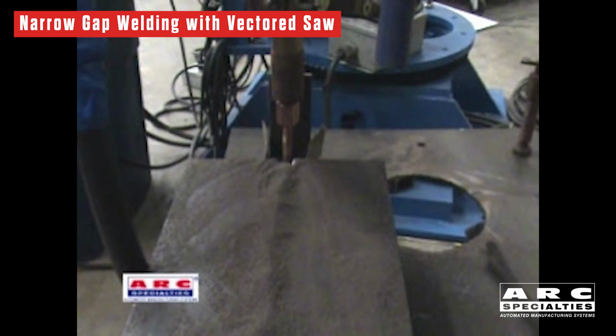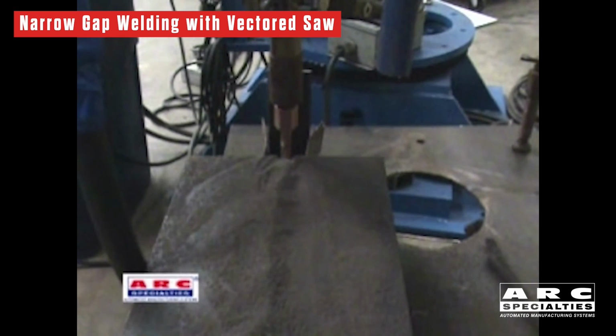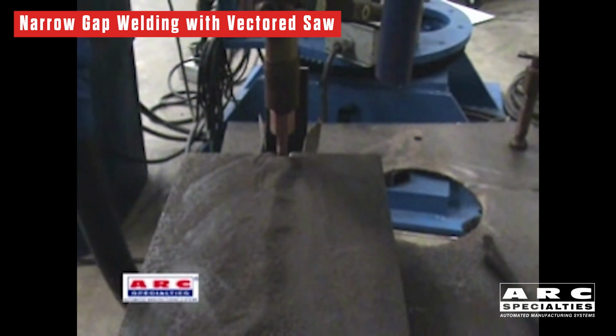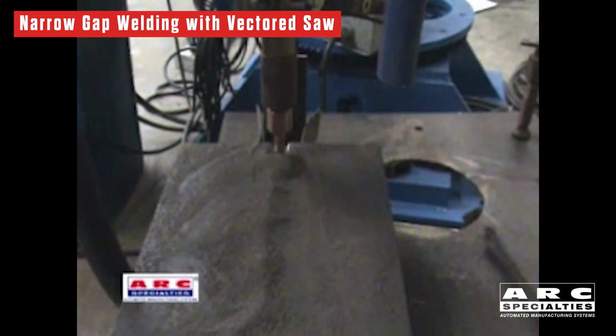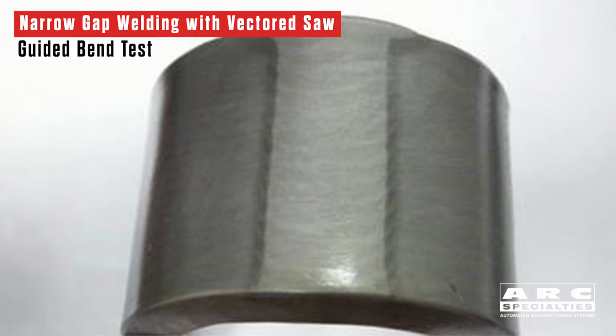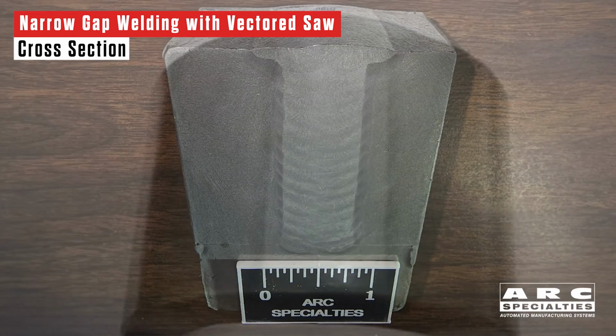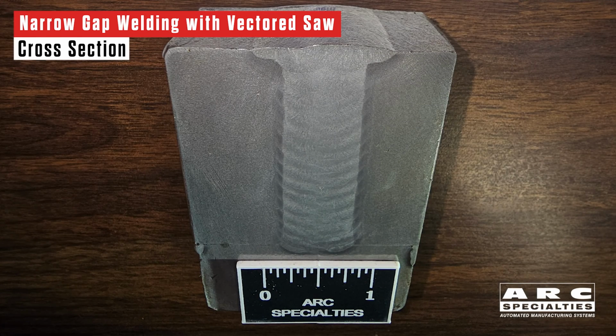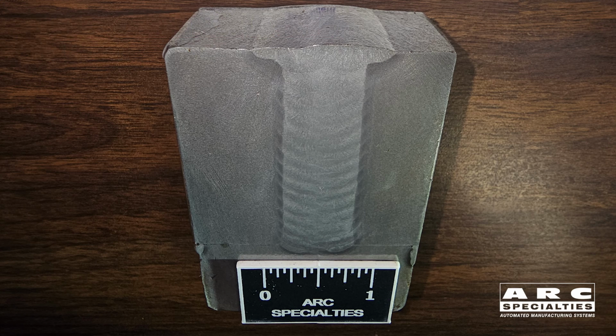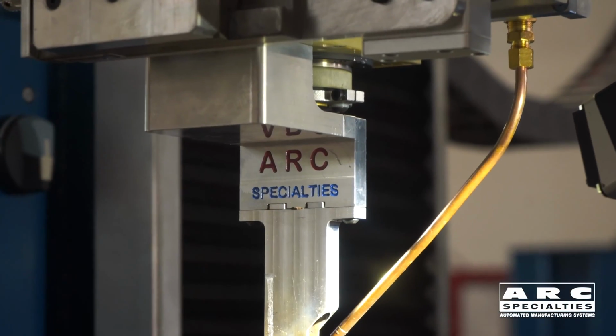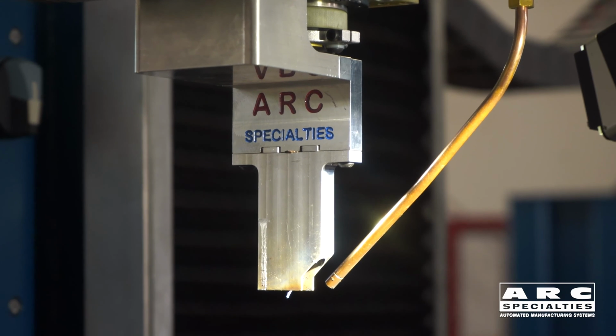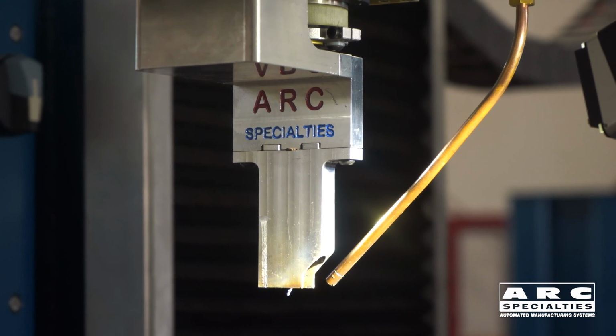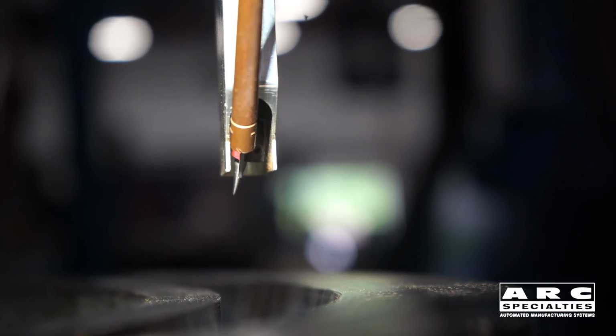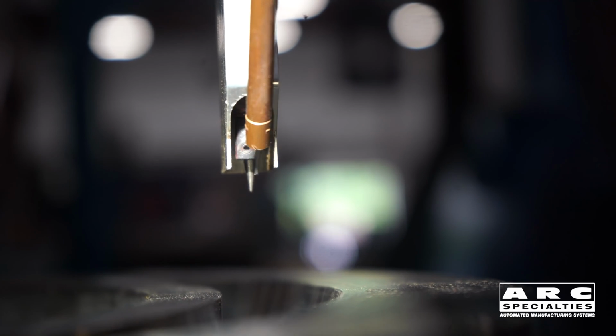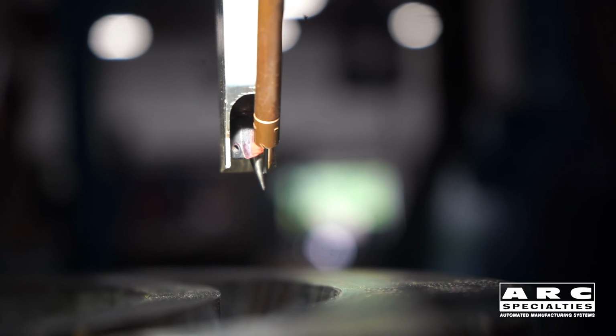Unfortunately, the Fukushima disaster occurred and people lost interest in nuclear power at the time. Well, that's coming back, and that's what we're talking about. So the next effort we made was with a commercial gas tungsten arc narrow gap torch. It worked fairly well, but we recognized several shortcomings, and so we decided we'd build our own. We now have a torch that has dual servo axes. One axis rotates the torch, so we're able to oscillate the tungsten back and forth and wet the wall of the joint that we're trying to weld.